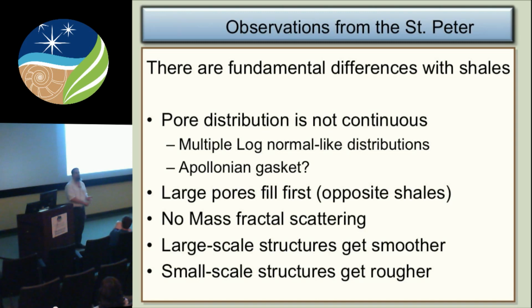We see that here, unlike the shales, it's the large pores that fill first. I didn't point this out earlier, but you noticed in those scattering patterns there wasn't a big bend in them. There's no evidence in any sandstone we've looked at for mass fractal scattering. That only seems to occur in shales, carbonates. You see it sometimes in granites. Often things that have, now obviously shale is a clastic material, but in things that are more chemical precipitates, like carbonates and essentially granites, is where you tend to see these mass fractal behaviors. The origin of that remains something that we're trying to work out.